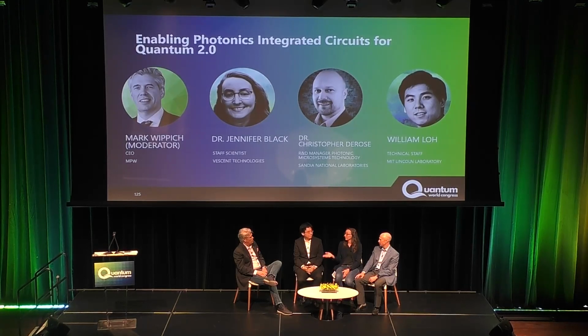And we were also employing, for example, lithium niobate, which is an active material. Because one of the dirty secrets in integrated photonics is that once you fabricate it, you can't really tune it. If it's a dielectric, it's passive. So some people will etch them after the fact or do all sorts of things. You can maybe heat them to move their properties a bit. But things like lithium niobate are actives, and so they give you functionality that you can't get with something like a silicon nitride. So anyways, we looked at these sorts of platforms using parametric gain to access wavelengths in the visible and combine multiple materials, which is a real technological challenge, real cutting edge R&D, and not something that's available in commercial foundries.